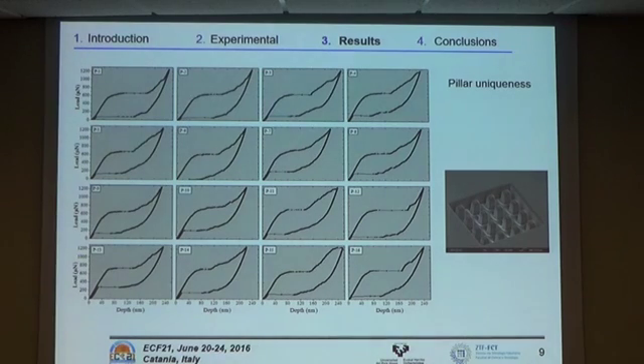In this slide, I show you the superelastic cycle for all the 16 pillars that have been milled in this array, and in general, we can say that qualitatively the behavior is similar, but of course there are some differences from one to the other. First of all, the critical stress for inducing martensitic transformation varies from one pillar to the other. The cycles are not completely the same qualitatively, so each pillar has an individual behavior or some uniqueness.